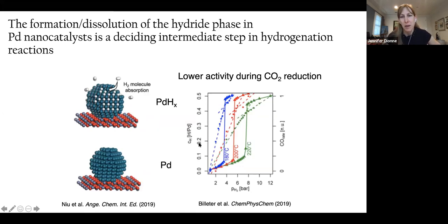Here's just one example from Billeter and authors, where they looked at CO2 reduction in palladium catalysts and found that as soon as the particle had hydrogenated, the slope of your production of CO during CO2 reduction was significantly reduced. So the formation of the subsurface hydride phase can have enormous impact on the catalytic activity of palladium-based catalysts.